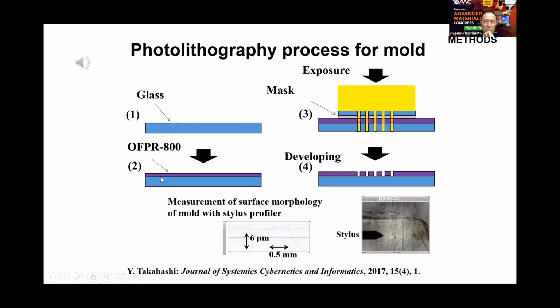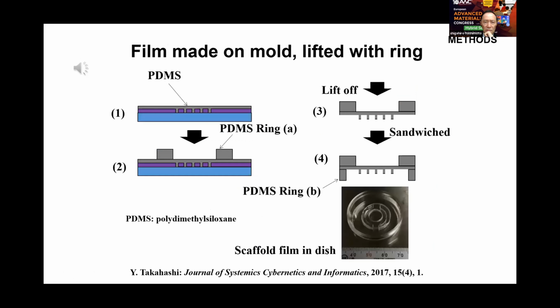Photoresist coating is controlled by several factors: viscosity of photoresist, rotating speed of spin coater, baking temperature and time, and intensity of laser drawing. Dimension of the surface topography on the mold is measured by stylus profiler to confirm design parameters: thickness of film, interval between markers. Mechanical properties depend on the volume ratio of PDMS to curing agent. A PDMS ring of diameter 15 mm was placed on the thin film of PDMS. After the film was baked with the ring, the PDMS film with PDMS ring was carefully peeled off from the mold.